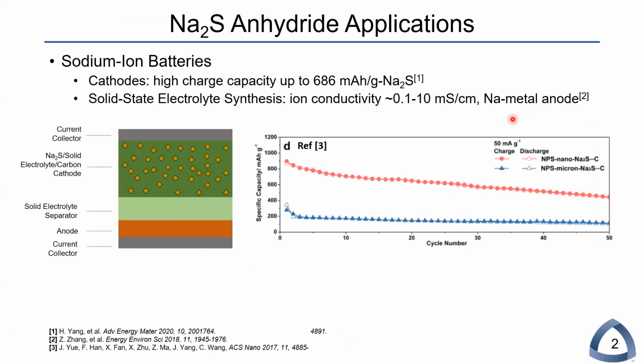Anhydrous sodium sulfide is emerging as a key chemical for the fabrication of sodium-ion batteries. It can serve as an active cathode material with a high charge capacity approaching 700 milliamp hours per gram, and it's also a key precursor for the synthesis of sulfide-based solid-state electrolytes, which possess high sodium ion conductivities on the order of 0.1 to 10 millisiemens per centimeter, and they may also enable the use of high-capacity sodium metal anodes.